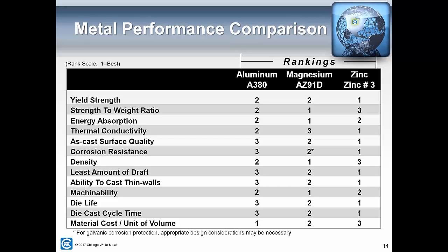Being able to cast thin walls is also best for zinc. So, you look through these and you see a lot of number ones for zinc or magnesium, not so many for aluminum until you get down to the bottom, whereas material cost is generally best with aluminum. And it's not true, of course, for every application, but cost is probably a bigger driver than many of these other factors, and so that's why aluminum still leads the way in terms of die casting. By far, there are more aluminum die castings than any other material.